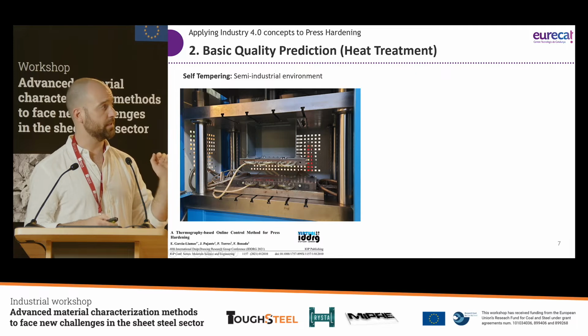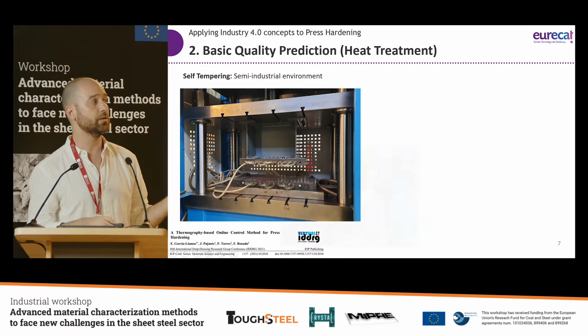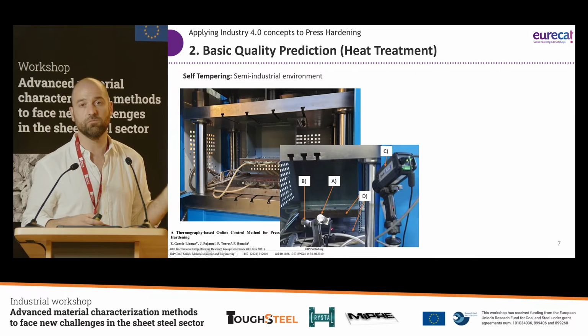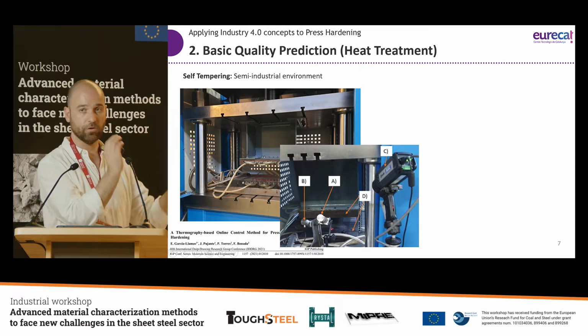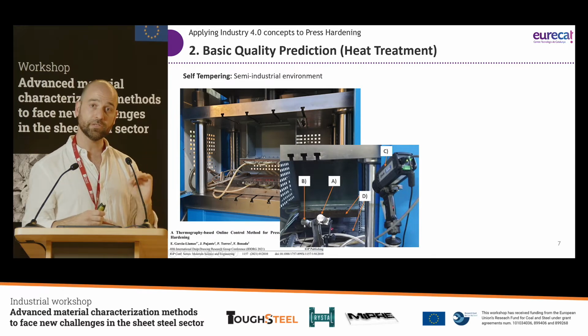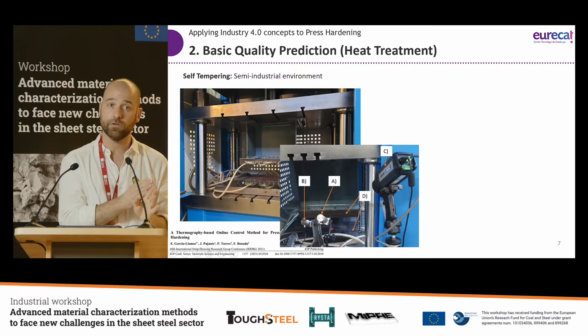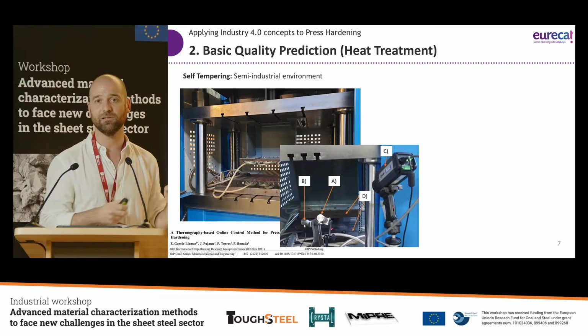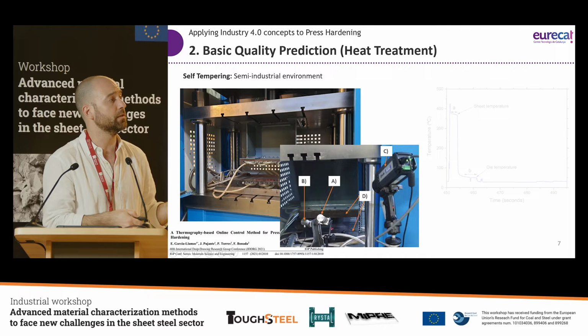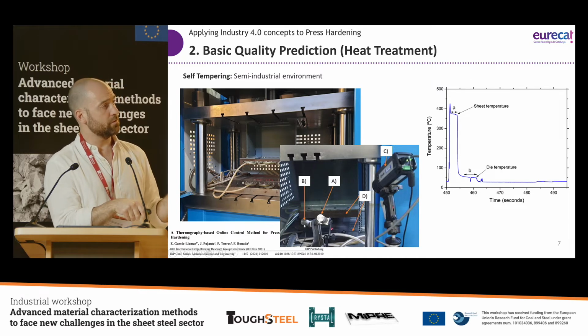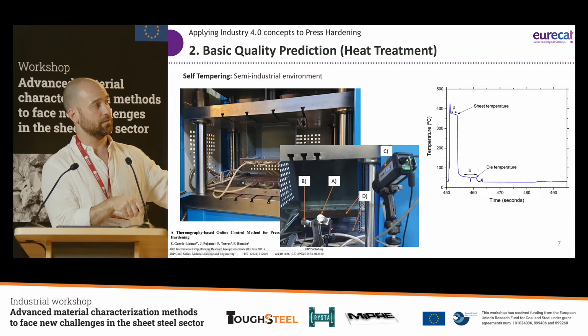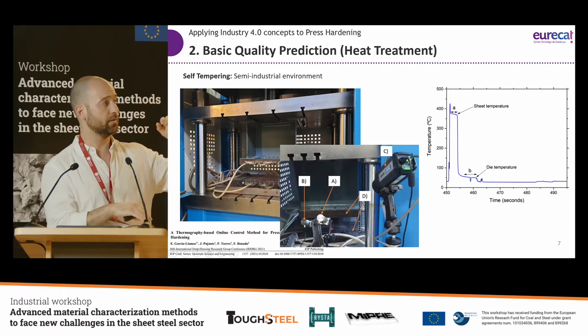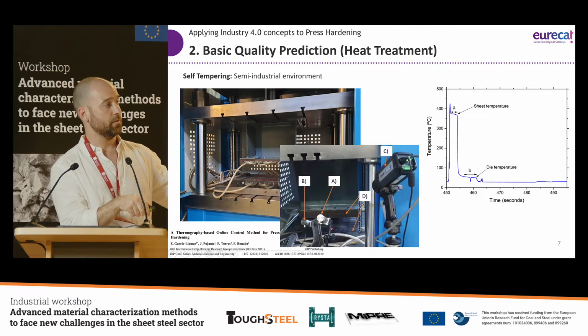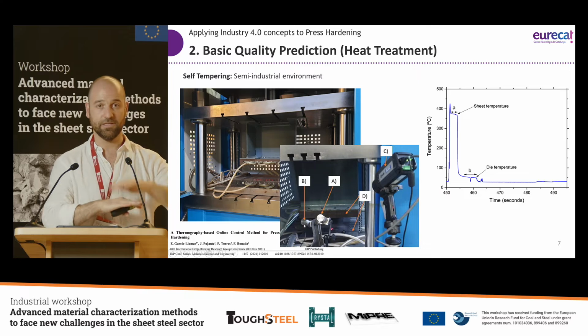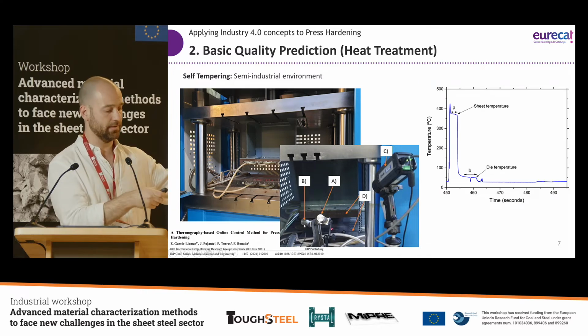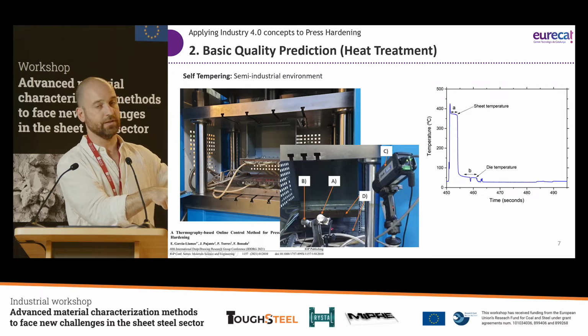Afterwards, we went to a semi-industrial environment, and what we wanted to do here is, okay, we took some thermal cameras, some pyrometers, we put them all around our press, and the idea was to measure temperatures to see if somehow we could monitor the heat treatment using this very simple equipment. If we see, we could measure more or less the sheet temperature once the die opened, and when it closed, then we can see, when we open the die, we see a plateau with the sheet that's a little bit hotter, and then we take the sheet out, and when we see the temperature of the die, it's a little bit complicated.